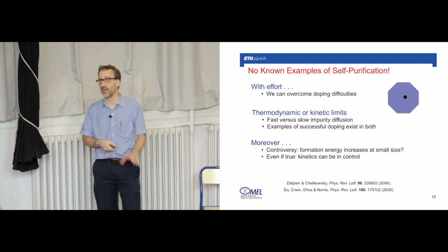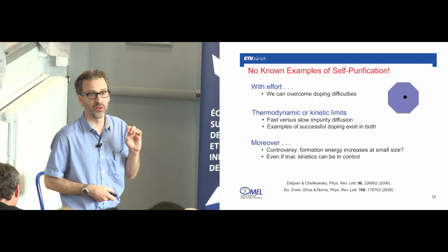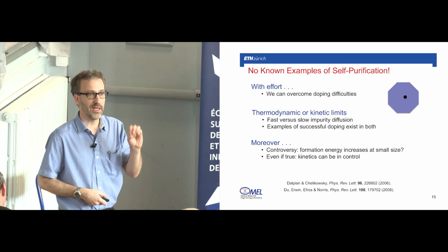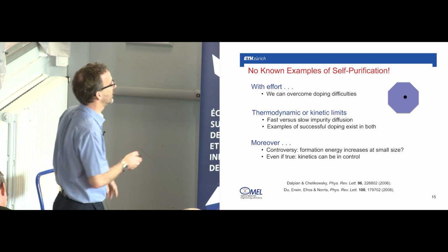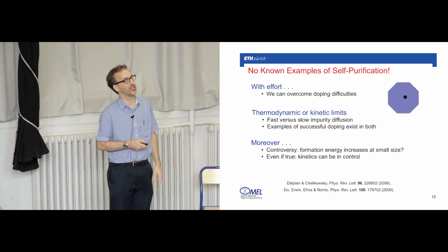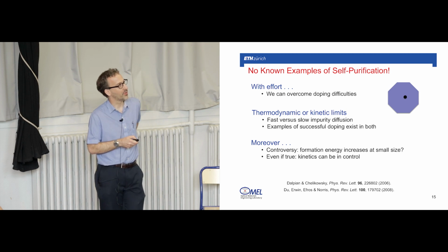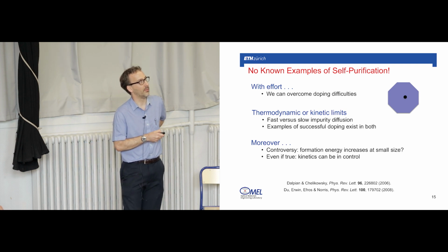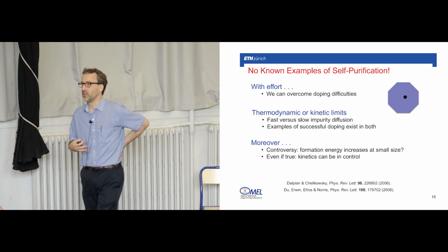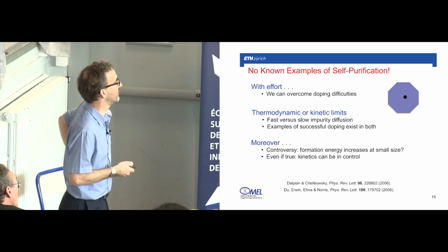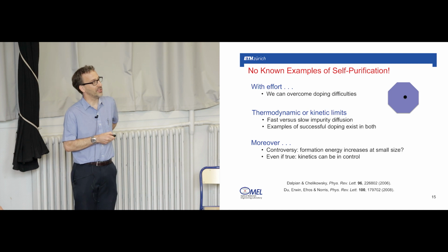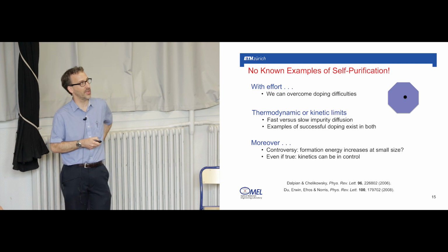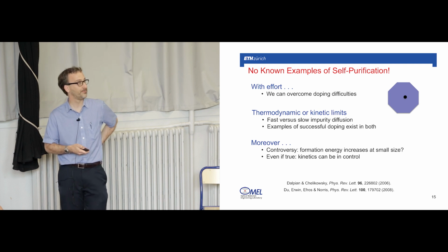So the bottom line is that, as far as I know, there are no known experimental examples of self-purification. If anybody has an example they want to share with me, I would really like to know it, because I can't rule out that there's such a process, but as far as I know, there are no known examples of this process. And with effort, we can overcome all the doping difficulties as long as the impurity has sufficient solubility. So we have these two limiting models, thermodynamic or kinetic limits, where you have either fast or slow impurity diffusion, but we have successful examples of doping in both limits.